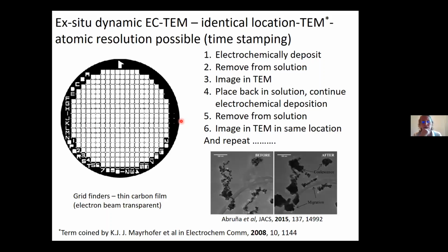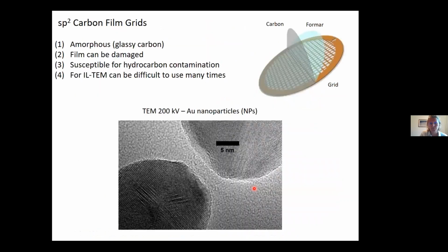So this is an example of a study by Hector Abruña from Cornell. He was looking at platinum nanoparticles on carbon supports, these sp2 carbon supports. And after cycling under fuel cell conditions, he was showing that there was an agglomeration, a movement of the catalyst nanoparticles. And this is something we're interested in as well, this idea that you can design the most perfect catalyst, but what happens to it in the real environment. So a lot of my work is very much geared to commercialization or real application. So this is identical location TEM.